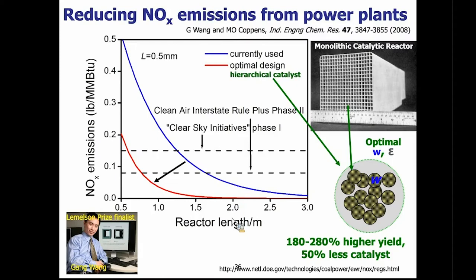And so when you start implementing this, it's very interesting that you can use it for, say, reducing NOx emissions. It's an important problem with nitrogen oxides, a pollutant which comes from power plants. It's well known to use selective catalytic reduction reactors. So you can have these wash coats on the inside of these monoliths, which you see on the right. But what we changed is to propose a hierarchical design of the catalyst with a controlled porosity.